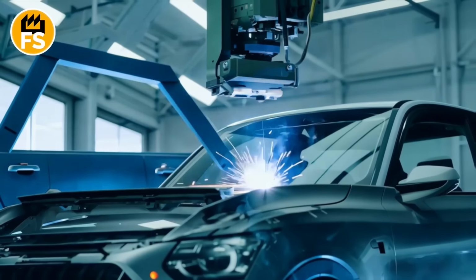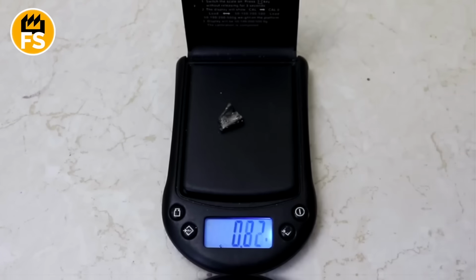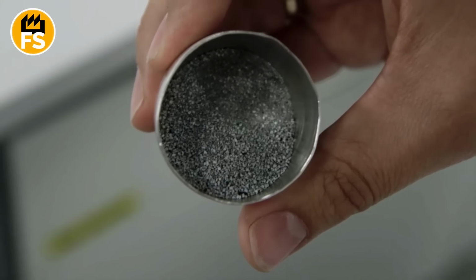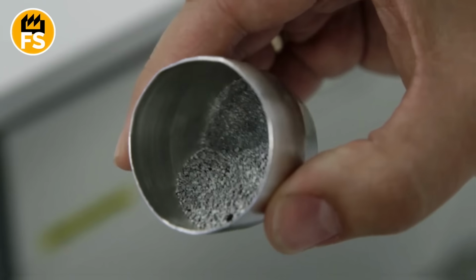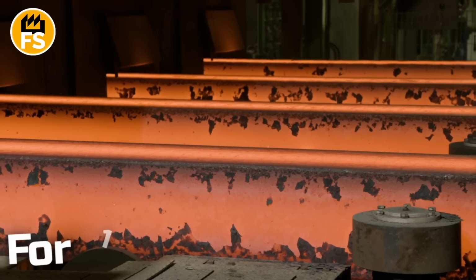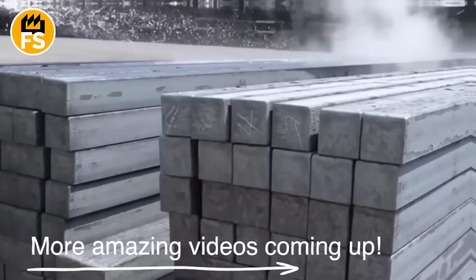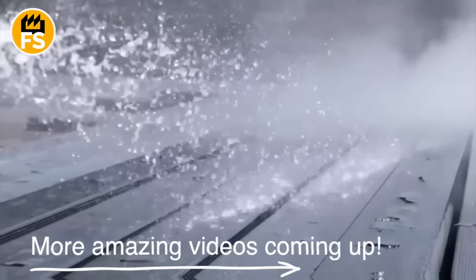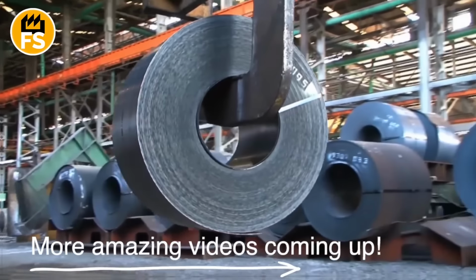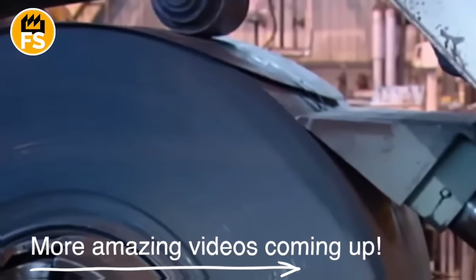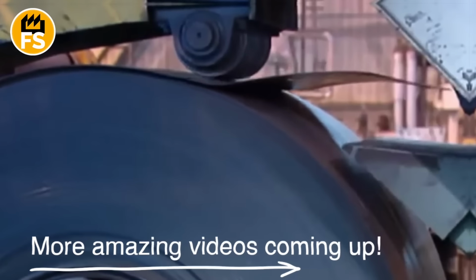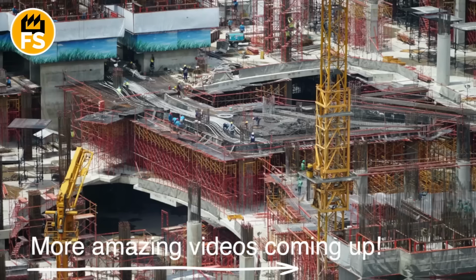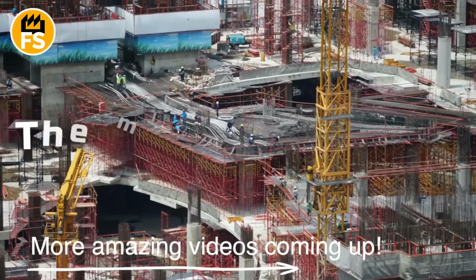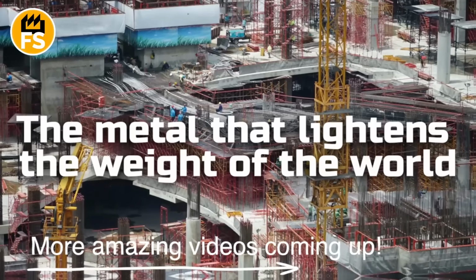The key feature of vanadium is that it works in microdoses. To get a noticeable effect, just tenths or even hundredths of a percent are enough. This means that for 1 ton of steel, only grams of vanadium are used, but those grams can boost yield strength, toughness, and durability by tens of percent. At the scale of millions of tons of steel, this delivers massive savings in metal, energy, and transportation costs. That's exactly why vanadium is often called the metal that lightens the weight of the world.